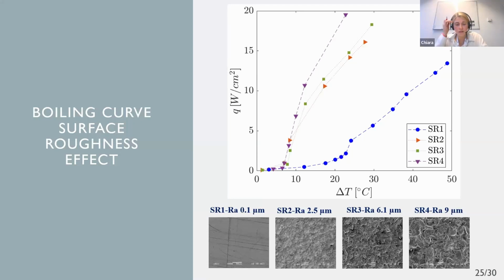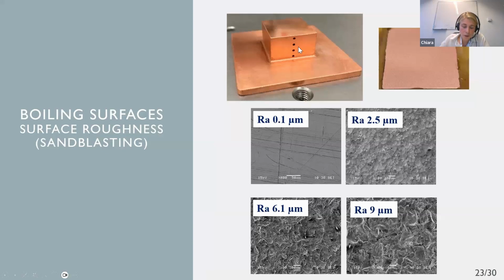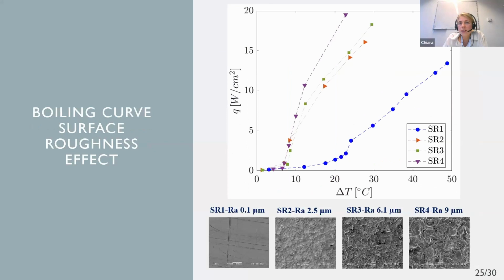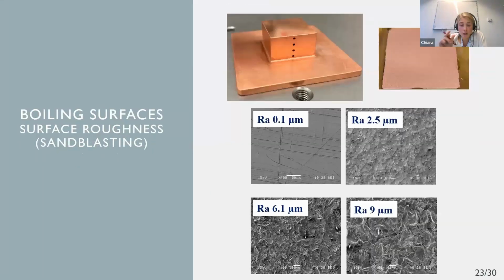Thank you for the question. In fact, I haven't specified that. The SR1 is essentially the one I'm showing here on the top. This copper block was CNC machined, and then we asked the manufacturer to polish the surface. Then all the samples were characterized in our material department with an optical profiler to measure the roughness. And as you can see in these images, we also did some SEM, scanning electron microscopy, to investigate the structure. For the microstructures, we wanted to measure the uncertainty of the machining, so we also evaluated the uncertainty on the geometry.